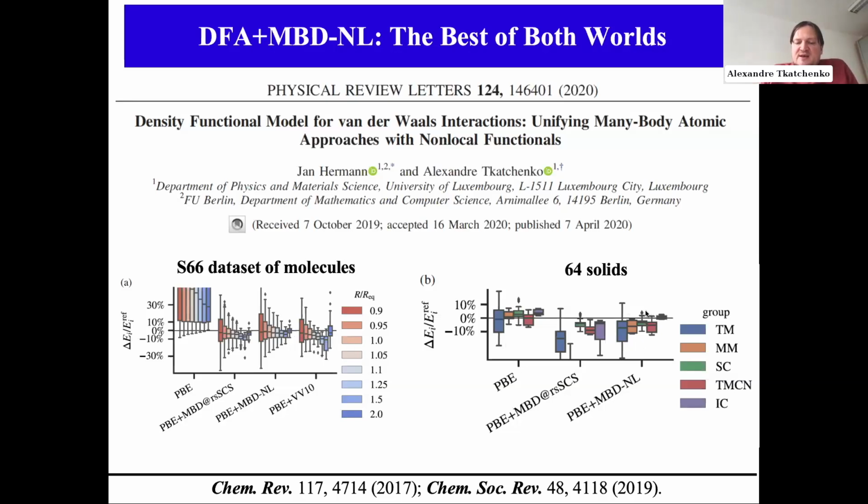And also for solids, the performance is not far from the performance of the parent PBE functional. Now, it's pretty hard to beat PBE. Actually, no one really beats PBE still, I would say, among local, semi-local DFT functionals in terms of performance for solid state. So PBE plus MBD-NL works as well as PBE. In contrast, the original MBD functional fails for many of the solids because of so-called overpolarization problems. And so you cannot even carry out MBD calculations for many of the highly polarizable solids.